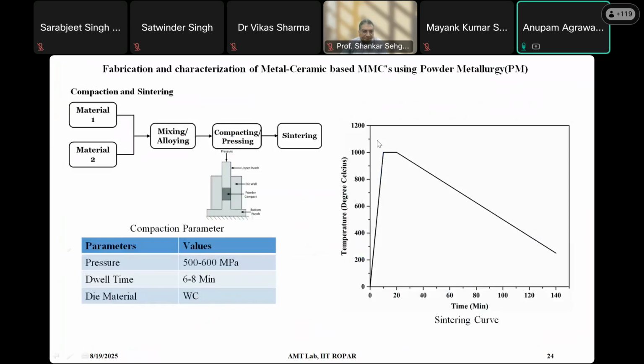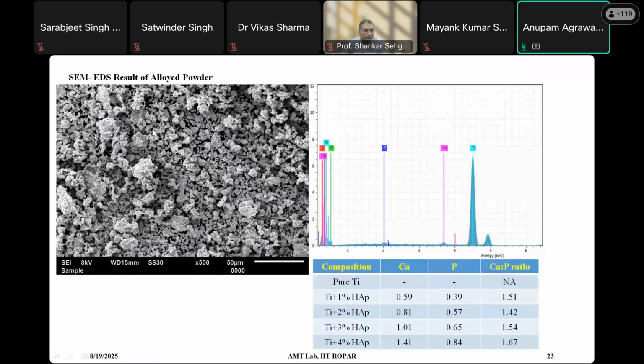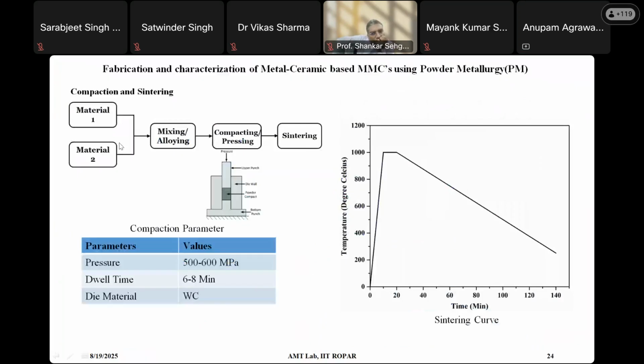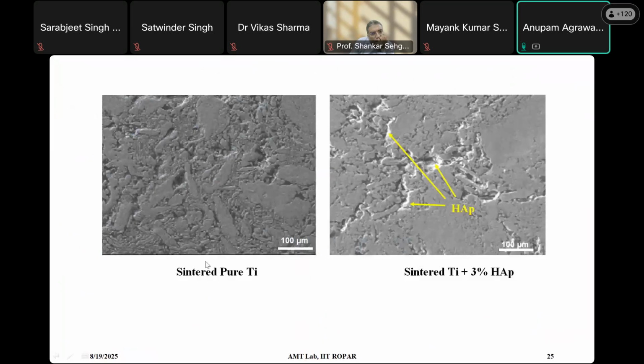For the compaction, we try compacting all of these and make sintered samples. So we took this material, did the compacting and pressing, and then the microwave sintering, and fabricated the sintered samples of pure titanium and different percentages. Here we have shown titanium 3% HAP. These white spots show the presence of HAP. HAP was found to be decently homogenized, not ideally, but decently.